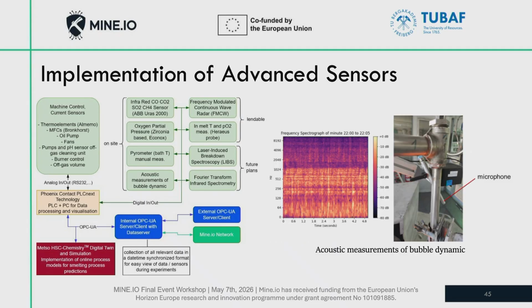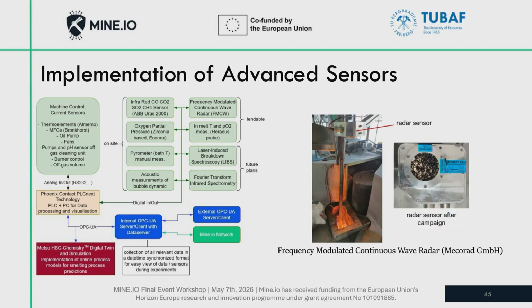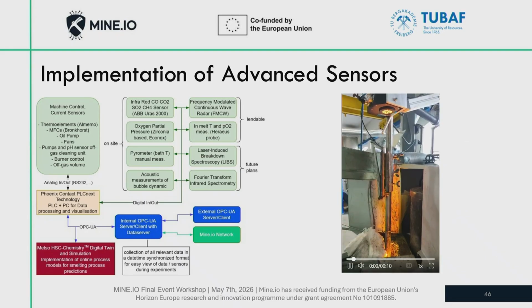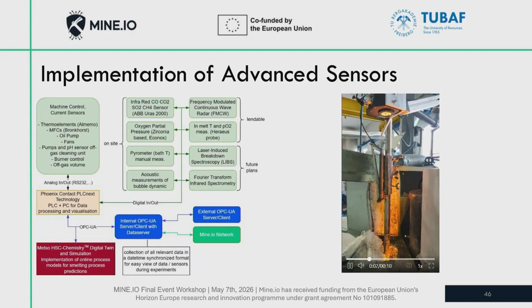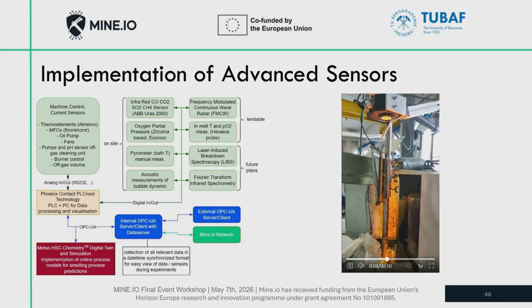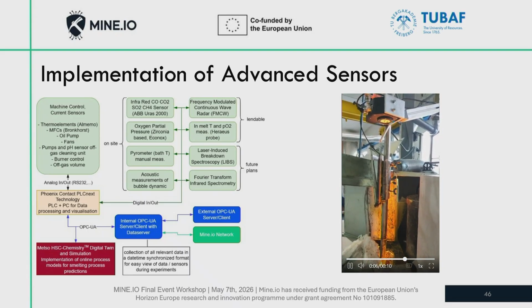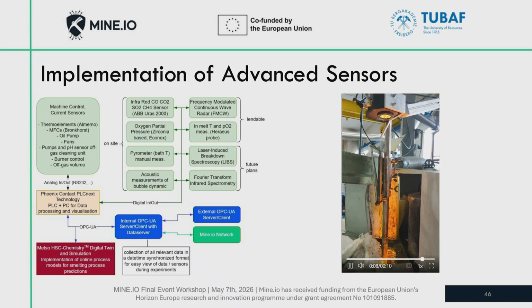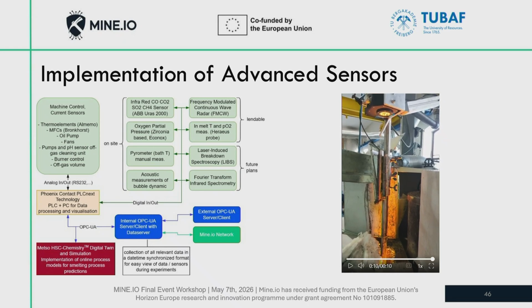Coming to some more advanced sensor systems, acoustic measurements, which I come to in a minute. Here you can see our setup with a microphone in the top of the furnace and also the radar sensor for distance measurement and bath level height measurement. You can see the action for a short moment. You can hear the acoustics and the turbulence inside of the furnace and a very violent splashing of slags and metals.